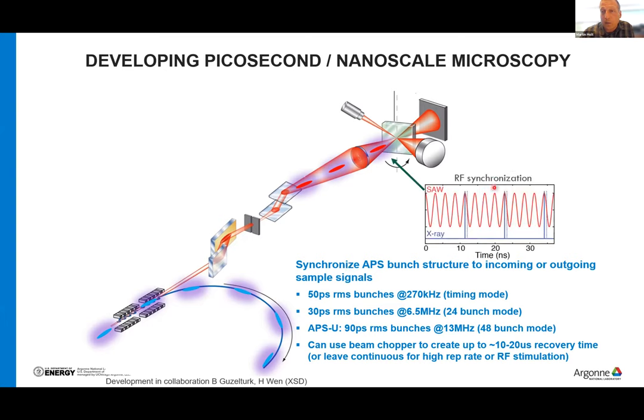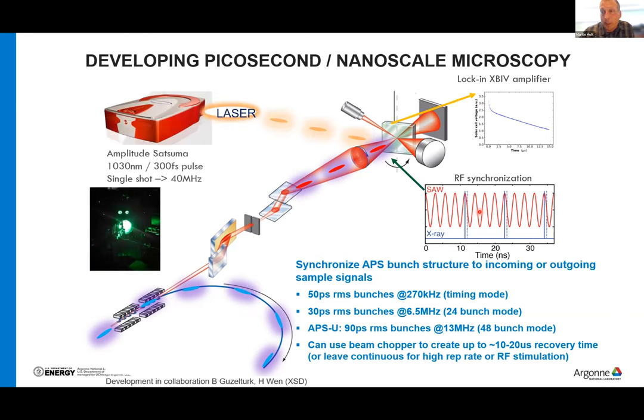So we can either synchronize this with an RF stimulation of the sample, which we use to create acoustic waves, but could also be used to create heat and piezo response in 3D device stacks. We can look at the electrical signal coming out, which lets us look at carrier recombination rates in photovoltaics, as well as near interface band activity and transport that's similar to transient spectroscopy, just the X-ray equivalent of that. And of course, with a laser, we can optically pump photo-excited phase transitions and watch them in real space and in this time sense. And we can also treat these beams by deleting some of these bunches using a high-speed chopper to give you a flexible dark time for system recovery.